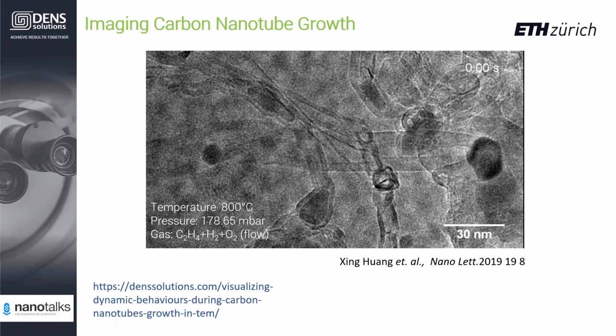Here is a recent work from ETH Zurich about carbon nanotube growth on iron oxide nanoparticles. I will put iron oxide in quotation marks here, because iron oxide is only the starting composition on the chip, while researchers from ETH Zurich found from atomic resolution images under active environment that the active particle is actually iron carbide. And on the basis of the real-time imaging,